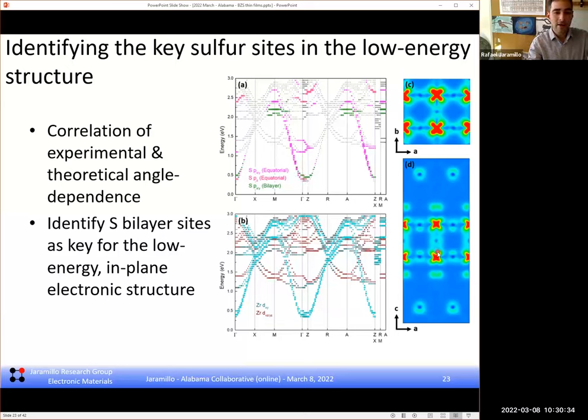So what we see here is if you look at these electron density maps, looking from the top down, here looking from the side, you can almost see the electron waves propagating freely in the layers. And it's kind of funny how these pi star bonds here between the sulfur p orbitals and these zirconium d orbitals, you can kind of imagine the electrons flowing through the crystal. Now, this is where the data ends and my imagination begins. But I'm trying to explain what right do these crystals have having such high charge transport mobility? And I think this strong degree of covalent overlap is the reason why.